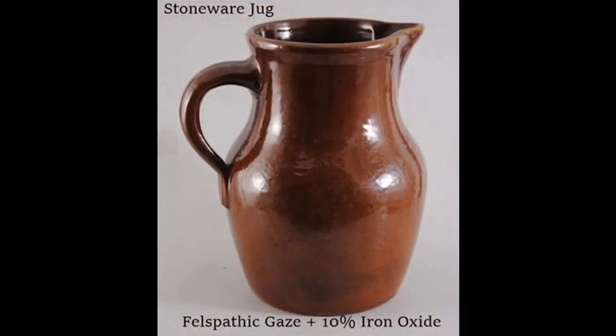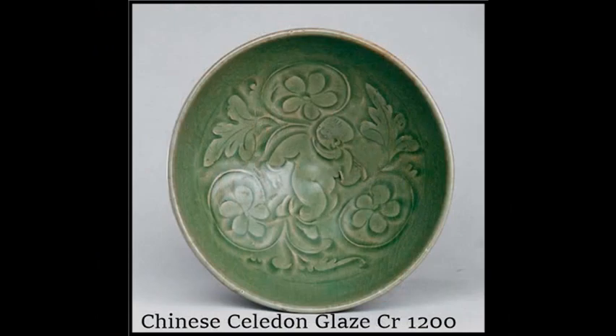This brown jug is glazed in a feldspathic glaze with about 10% of iron oxide to give it its rich brown colour and fired in oxidizing conditions. A very well-known glaze, the celadon, results from the addition of a very small quantity, up to about 1 to 2% of iron oxide in the glaze, which is fired under reduction conditions.